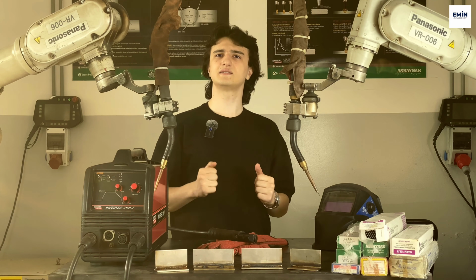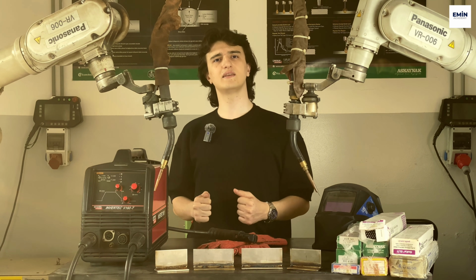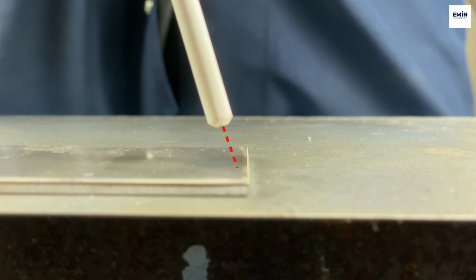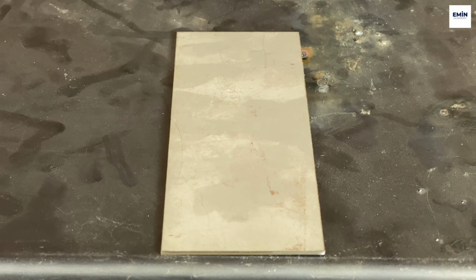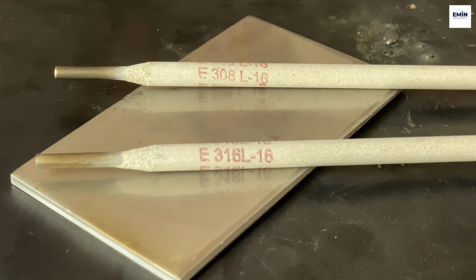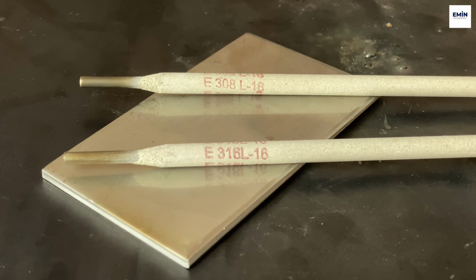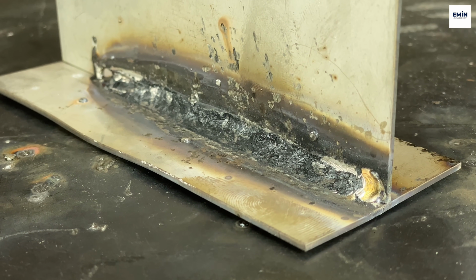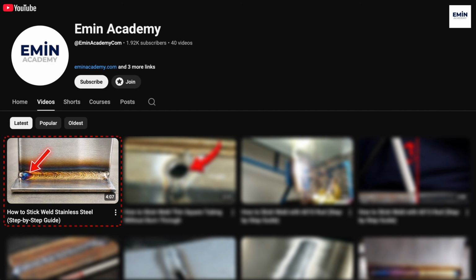Gray and black. Gray and black colors are an indicator that there are multiple errors. These colors usually show that the arc length was kept long, there's oil or dirt on the surface, the electrode is damp, or the wrong electrode was chosen. If your weld bead is in gray and black tones, you can achieve the ideal light gold weld color by watching the How to Stick Weld Stainless Steel video on my YouTube channel.